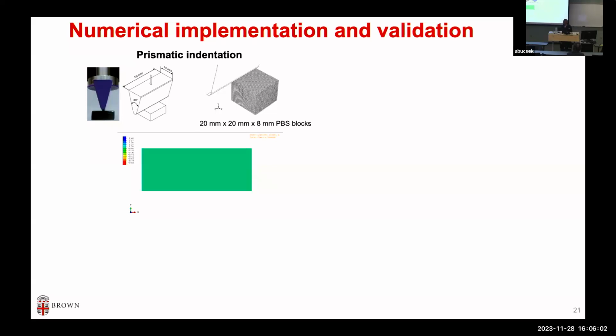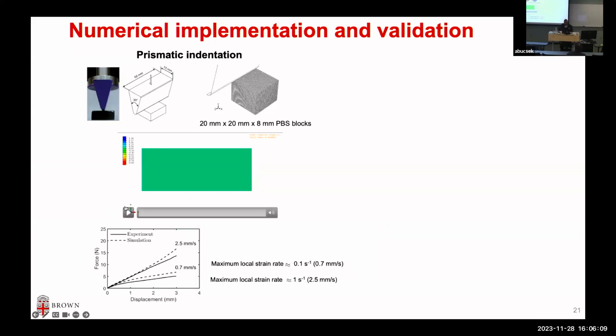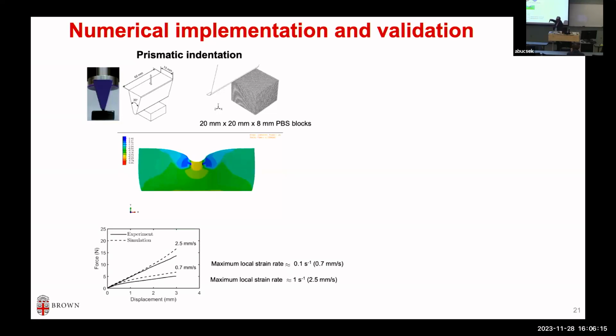We can simulate in Abaqus. If I can find my mouse somewhere. Right, so you can see the strain rate and strains are very inhomogeneous, a three-dimensional geometry being pulled in on one side, deformed on one side. But we looked at the prediction from the different velocities or different rates, force versus displacement, that we can measure independently, and we compare it against the simulation. You can see it does a reasonable job. So now we have some faith in the three-dimensional model, that it has a lot more capability.